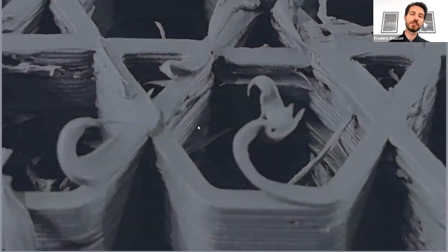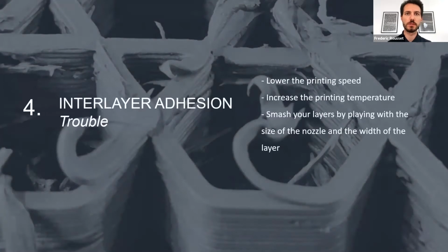For this trouble, you won't find it with polymer filaments or even ceramic filaments. It's quite rare, even for this filament; we don't see it that often. But if it happens, the best solution that we found is to lower the printing speed. As I said, 5 millimeters per second should resolve the problem completely. If you still have some problem, increasing the printing temperature can be good as well.